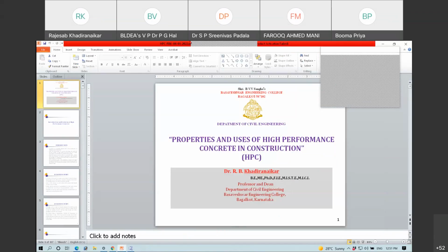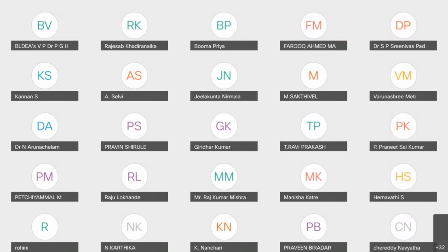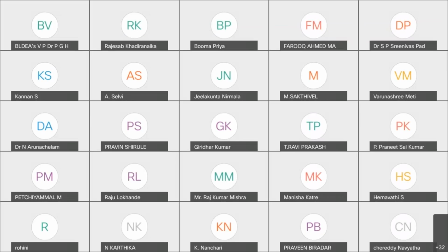Which type of superplasticizers are preferable? Fourth generation are better. It depends on what is the water cement ratio that you are going in for. If you are going in for the range of 0.3 or 0.32, then even SNF, SMF is okay. If you are targeting say a water cement ratio of 0.2 or 0.25, then carboxylic based, that is fourth generation, generally called carboxylic ethers and all that. So you have to go for that. It depends on what is the water cement ratio that you are starting with, and then what is your targeted workability. That also matters. But HRWRs are better than your SNF, SMF, and those things.